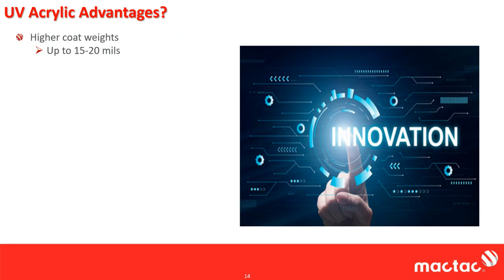One of them is that with the UV acrylics, you can get much higher coat weights. Solvent-based adhesives, you pretty much top out about 5 mils. There are some UV acrylics out there that are coming there. They're free radical cured, and the vendors out there are touting up to 15 to 20 mils in thickness.